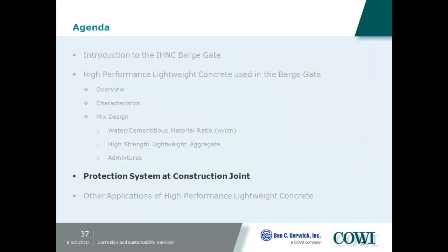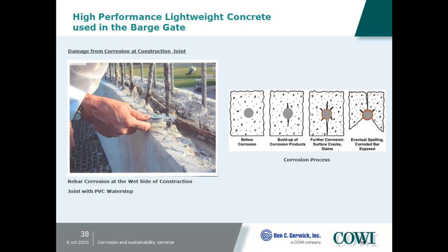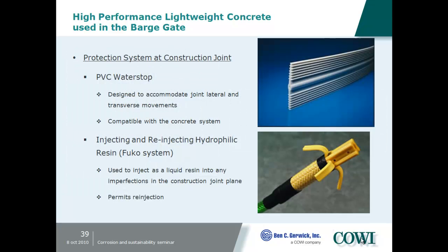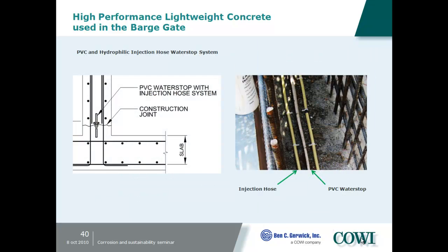But again, we had to look a lot at the joint construction here. This is not our joint, but that's a typical problem where there's a water stop. And if you don't get the joints right, you can have corrosion happening that could lead to spalling. And to help provide a guarantee of that, on top of the water stop, we also have this Fuko injection, re-injection with a hydrophilic resin, to make sure and guarantee that there isn't a problem.